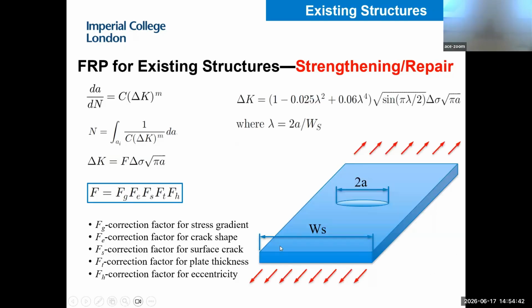For example, for a steel plate with a through-thickness crack in the center, you have a remote loading, uniformly distributed along the edge, which is perpendicular to the crack. Then there is a theoretical solution for the stress intensity factor at the crack tip - this is the formula given in the design standard. So you know the stress intensity factor, you substitute delta K into the Paris law, then you do integration from one crack length to another crack length, and you can work out how many fatigue cycles you need - that means you can predict the fatigue life.